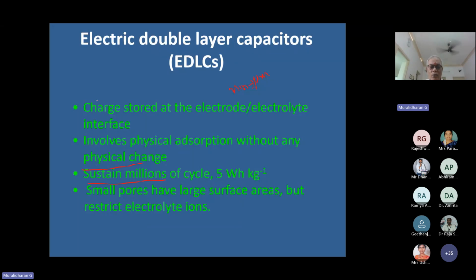Unlike our lithium batteries today, the lithium battery performs exceedingly well for the first 3 months. Charge it in the morning, and up to next morning at least 30% of the charge remains. But after 6 months, you charge it in the morning, and again in the evening you have to charge the battery. They don't last even 1000 cycles in real value. It's a problem. But if you use EDLCs, the electric double layer capacitors, they can sustain millions of cycles. You don't keep spending on the battery, and this is good.